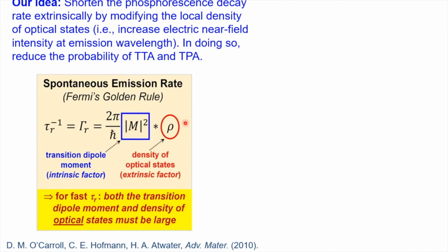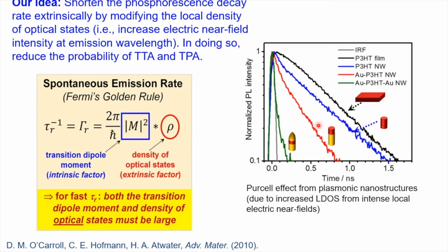But in our case, we're focusing on tuning this extrinsic factor, the density of optical states, using metasurfaces. And this is built upon a fairly well-known idea, at least in the plasmonics community, where you can accelerate or increase the rate of spontaneous emission by coupling a light-emitting material to a plasmonic nanostructure, a metal nanoparticle.